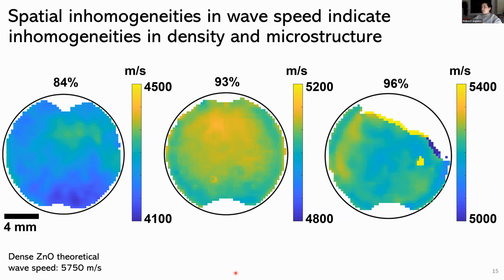So this already kind of gave us some of that information. The other thing of note, though, was that even though we were getting fairly high relative density, so for this last sample over here, and by the way, these are all zinc acetate samples, you see that for the 96% dense sample, 5,400 was still way below that theoretical wave speed for a fully dense zinc oxide material. So that already started sparking some conversation about what could actually be causing the difference between these.